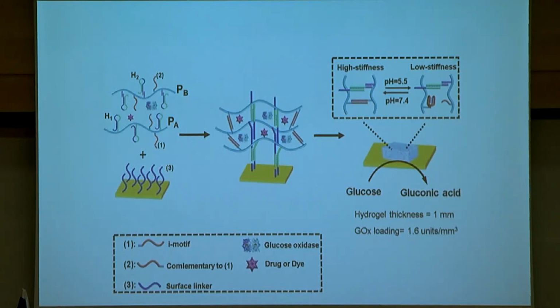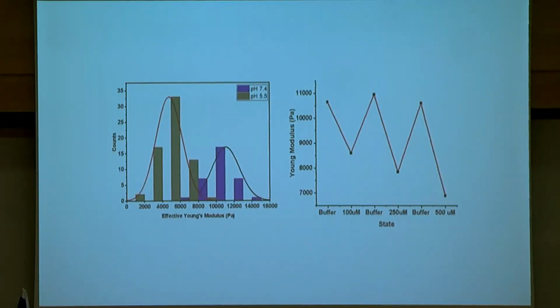Now, we can do it manually by changing the pH manually, but we can make it in a more sophisticated way to immobilize into this hydrogel glucose oxidase. The glucose oxidase oxidizes glucose to gluconic acid. Gluconic acid generates an acidic environment in the hydrogel, opens the hydrogel, and then as a function of the concentration of the glucose, we will release from this hydrogel our insulin. So this was the concept, and now I want to show you that we can go ahead and have it.